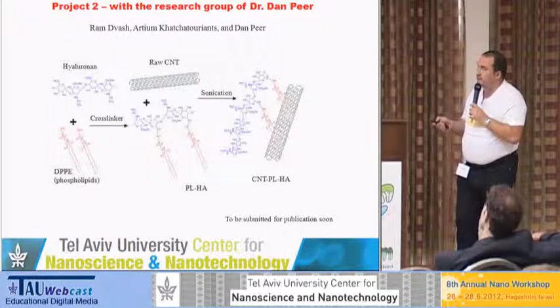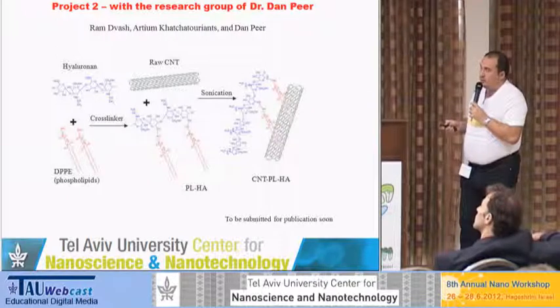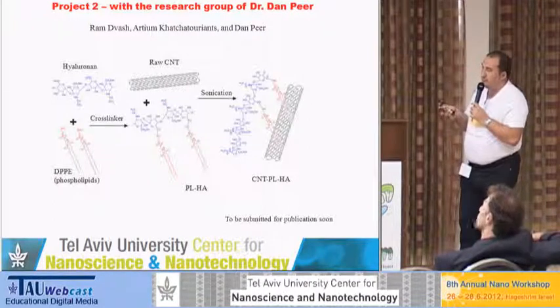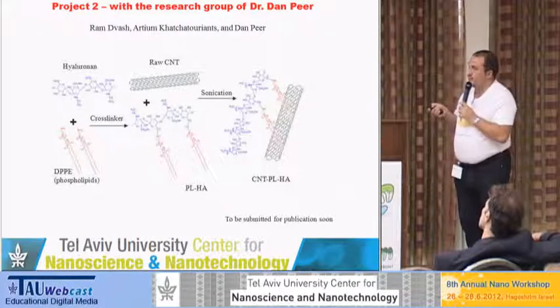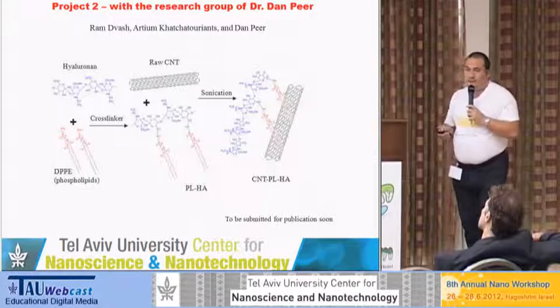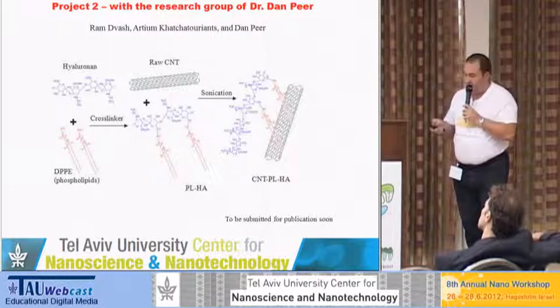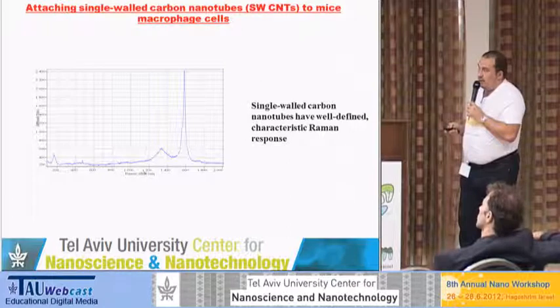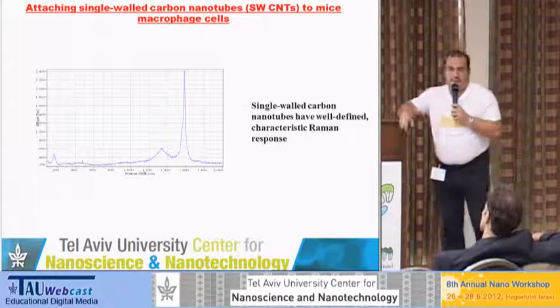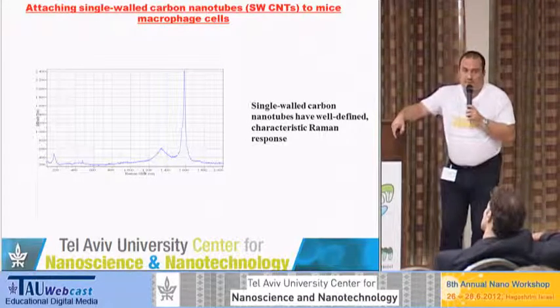So in this research, the raw carbon nanotubes were linked to a molecule of hyaluronan using phospholipids, which have hydrophobic tails. So you have this assembly, which is then directed by specific techniques to the membranes of the cell lines to be investigated. And here we used Raman for the characterization of these samples.